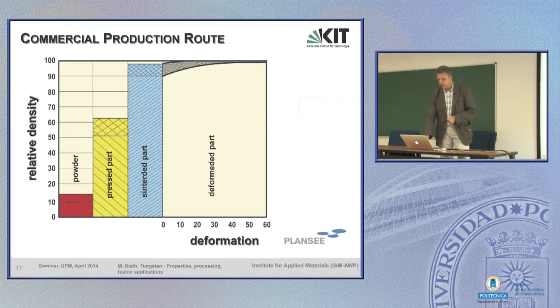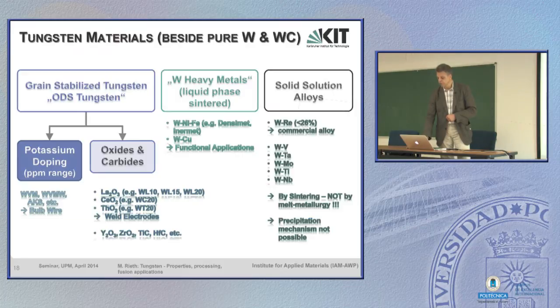deformed. The reason is pure powder has a very low density, around 15% or so. If you cold press it isostatically, you can reach densities around 60% max. After sintering, density increases significantly, but still the maximum you can reach during sintering ends at around 98% or so, so there is still porosity, which you usually don't want to have in the material. And to reach 100% density, you have to deform the material significantly. So this is the usual commercial fabrication or production.